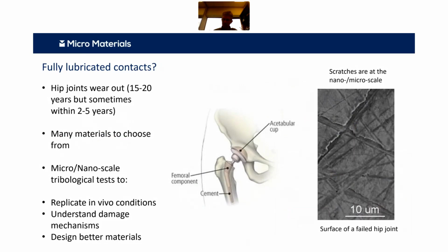So if we think about systems in general, biological systems, fully lubricated contacts are the ideal, with low clearances. So a lot of people are going to design these things on the assumption that you have this fully lubricated contact. But in fact, when you look at explants, essentially, as you see on the right, then you get very, very small scratches, often cross scratches that you see on the surface of failed hip joints. And particularly when these things wear out much more quickly than they're expected to. So there's lots of different ways to design this system, and there's a lot of work going on where the small scale tests are really helping inform the materials choice and the alloy development choice by replicating these in vivo conditions and understanding these damage mechanisms better.